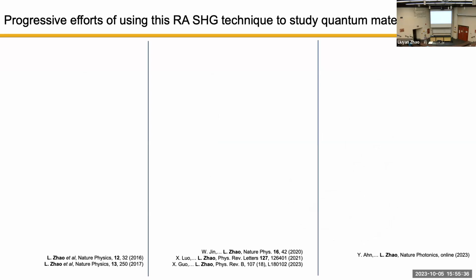Many people used it to look at structures of non-centrosymmetric materials or surfaces of materials, because a surface naturally breaks inversion. So when I started my postdoc in Professor David Hsieh's group at Caltech, we were wondering whether we can use nonlinear optics to study not only structure, but also electronic phases. At that time, there were many theoretical predictions of electronic or magnetic phases that subtly break inversion symmetry. It's a subtle process, so you don't usually see it if you use a not so sensitive SHG technique.